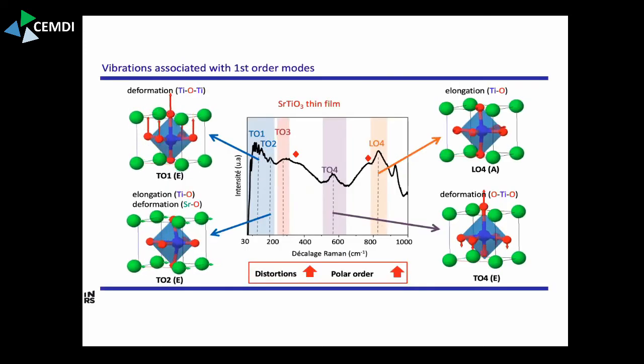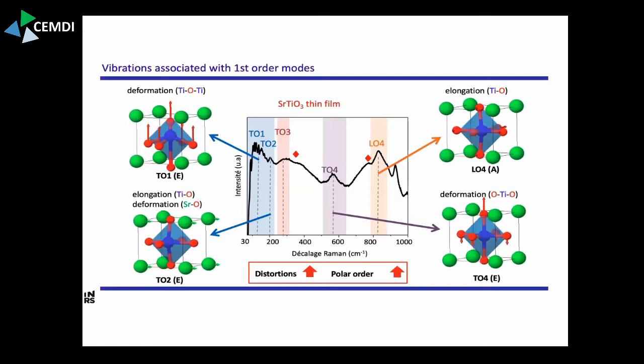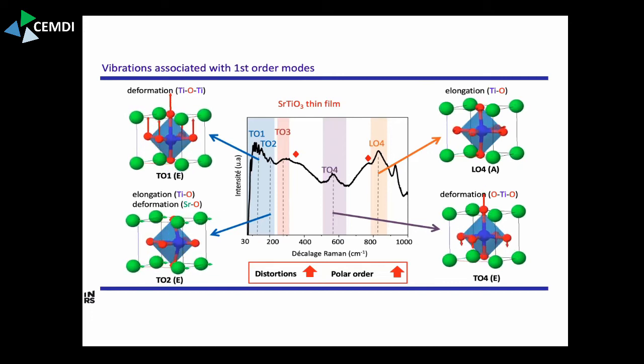And we could use literature to find out what's going on here. So this was still the easy part. We didn't really need to do any kind of simulation here. We could look up what people had already observed in strained strontium titanate. And you see that you have, first of all, a tetragonal distortion. And then you have these polar modes that oscillate here. This is actually carrying a dipole moment. This one carries a smaller dipole here. Tetragonal distortion again. Then you have just the oxygen octahedron oscillating with respect to the Ti4+ ion, and again that deformation here. So you get a couple of peaks that show up, and we understand what they are.